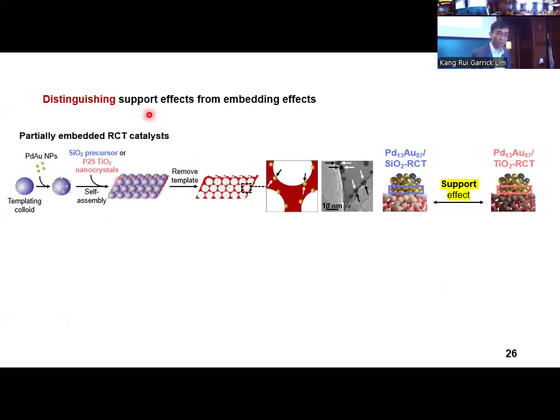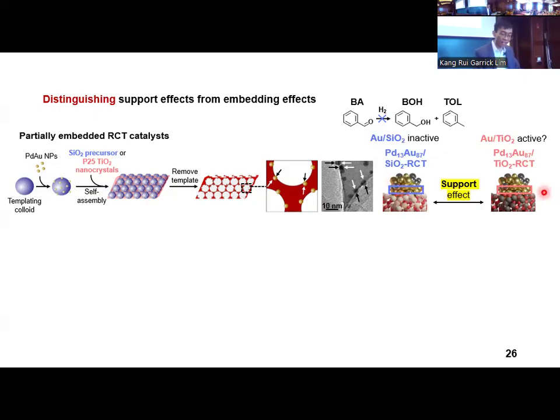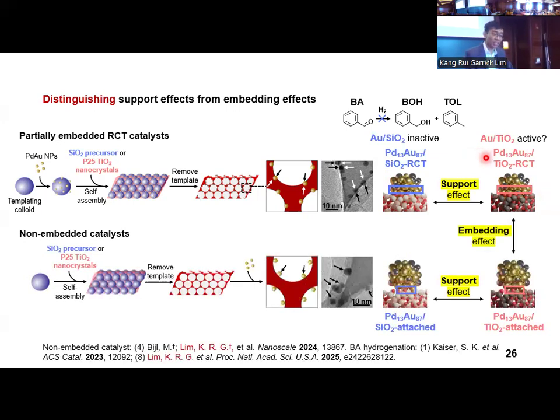To disentangle the support and embedding effects from each other, we first prepared RCT catalysts comprising palladium-13 gold-87 nanoparticles, partially embedded in either a silica or a titania support. The gold-rich nanoparticle composition allows us to compare the gold-silica interface, which is inactive for a probe reaction, against the gold-titania interface, which we hypothesize may be active for this same reaction. The dilute palladium content in the nanoparticles accelerates hydrogen activation or hydrogenation. As a control to investigate the effects of partial nanoparticle embedding on catalytic performance, we also prepared the non-embedded catalysts by immobilizing the same palladium gold nanoparticles onto morphologically identical silica or titanium support surfaces.